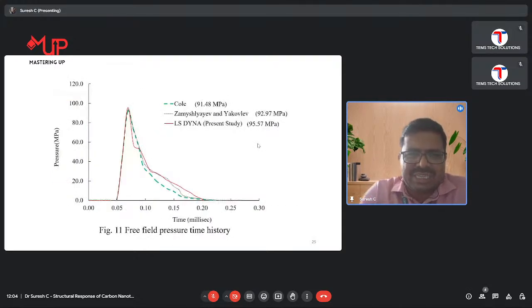Then we have measured the free field pressure, and we have compared it with the empirical relationships given by Cole and Zamyshlyaev. So for LS-DYNA, we have measured the pressure as 95.57 megapascal at a certain distance from the explosive, and at the same distance, if we calculate using Cole's equation, it was 91.48 megapascal, and from Zamyshlyaev it is 92.97 megapascal.